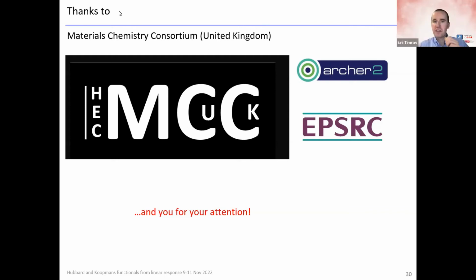Yeah, but actually it's a very good comment, though in practice we tested this idea and we found that orthoatomic gives more accurate results than atomic. It has a physical meaning also, because when you use atomic orbitals in the overlap regions, you apply the Hubbard U correction twice. And in practice, we do find orthoatomic to be more accurate.